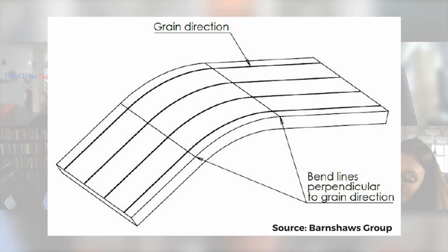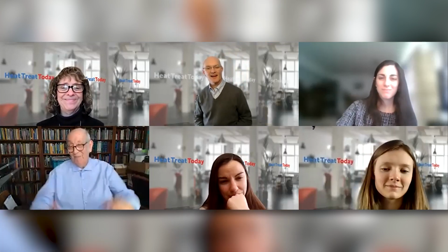We have found that if you stamp or cut component parts out of a plate with the rolling direction, or transverse or across the rolling direction, you can get vastly different properties out of the products. It's amazing that you can get tremendous distortion differences from heat-treated products, depending on whether you're stamping or forming out of a plate transverse or in line with the rolling direction. Most people don't even think of that. They take the plate, they move it into the stamping machine, and they could care less about the rolling direction. Then when the poor heat treater does his heat treating and distorts all the parts, the manufacturer says, "What's wrong?" By the way, that little example took only 9 years of my life to solve one time.